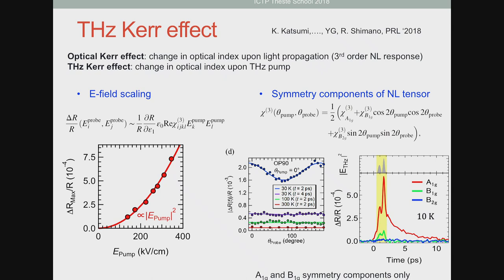You will have an A1G term that is going to be essentially independent of the light polarization. There is going to be a B1G term that is going to go as cosine 2 theta of the pump and cosine 2 theta of the probe. And there is going to be a B2G term that is going to scale as sine 2 theta. So very similar to the decomposition that I showed you for Raman scattering.